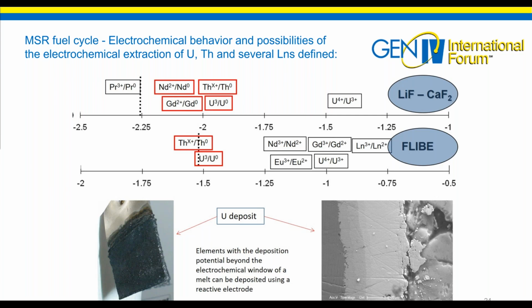The carrier salt for a molten salt reactor working in the thermal spectrum is FLiBe. However, the lithium fluoride-beryllium fluoride mixture, the lithium fluoride-beryllium fluoride eutectic, is insufficiently electrochemically stable, and therefore we had to solve how to do the electrochemical separation. We had to find a more stable carrier salt for electroseparation, and that's the lithium fluoride-calcium difluoride eutectic.